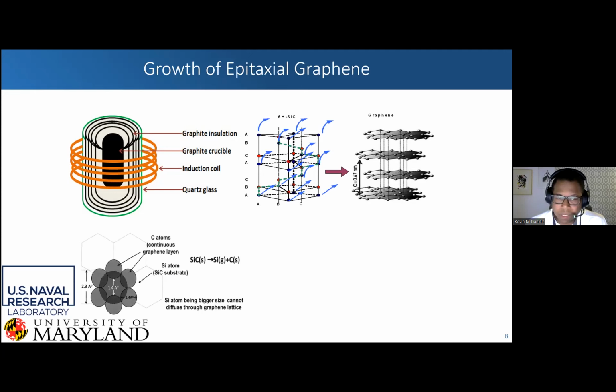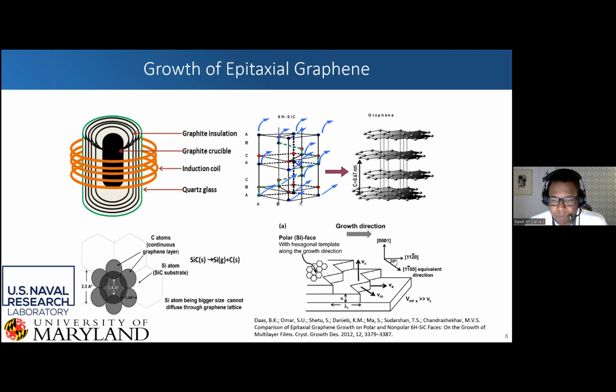And of course, if you're growing on a silicon face, there are limits. Typically, if you're growing on the carbon face, you're getting many layers, 4, 5, 6 layers. On the silicon face, because your carbon is forming on the surface, your silicon really has a difficult time escaping. And so in terms of growth, most of your growth is not going to happen through your 0001 plane, but your 11-20 and 1-100 directions, so your A plane and M plane. What this equates to is step flow mediated growth, where your silicon is desorbing there, and that's really where your graphene growth begins, as opposed to defect mediated growth that you typically see on the carbon face, or the opposite side of your crystal.